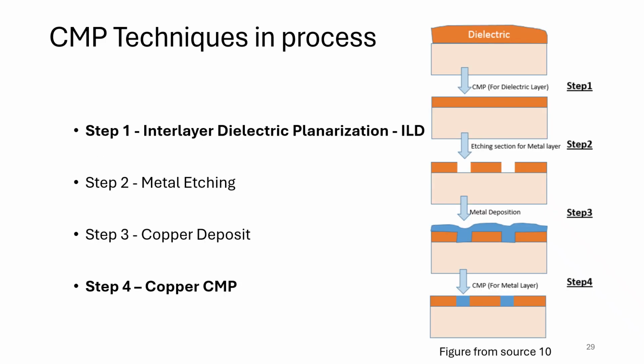To bring it all together, here we have a simple four-step example. Interlayer dielectric CMP is used to level a dielectric. Then metal patterning and etch is used for creating features. Then a copper deposit is used to fill them. And then finally, a copper CMP is used to clear the excess copper and leave metal only in the trenches and vias. This process will repeat multiple times, so the consistency of each CMP pass really matters to the whole chip building process.